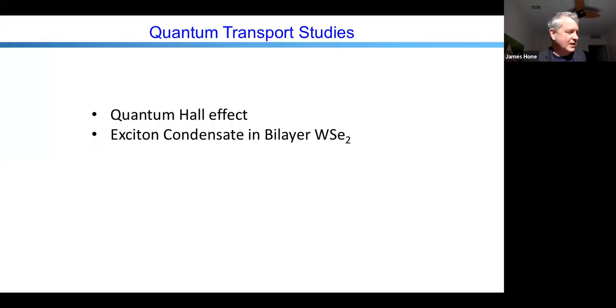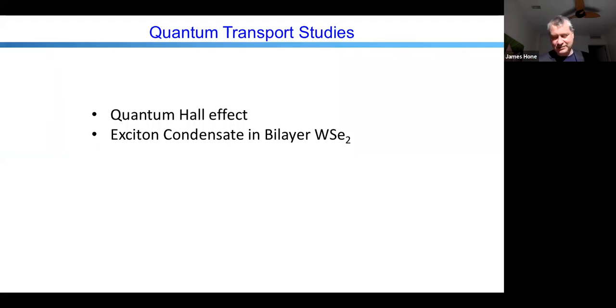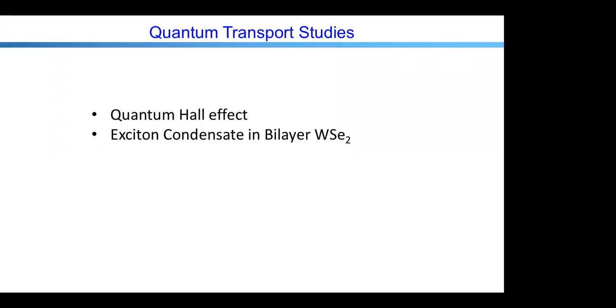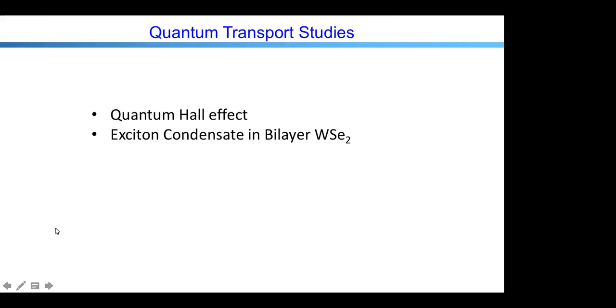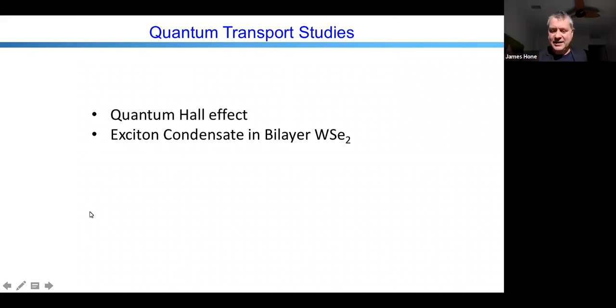That's the end of part one — our status update on this slow and painful synthesis process. But with this grinding away and paying close attention to defects, we've made great progress. One question from the audience: could you comment on the background carrier concentration in samples with such a low defect density? That's still to be determined. When we do scanning tunneling spectroscopy of monolayers, we see the Fermi level is inside the gap. The bulk crystals seem to be very slightly n-doped for both materials. We still have to do Hall effect measurements to nail down the carrier concentration, but they seem to be pretty close to intrinsic.